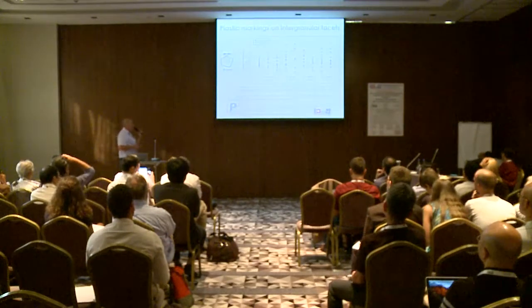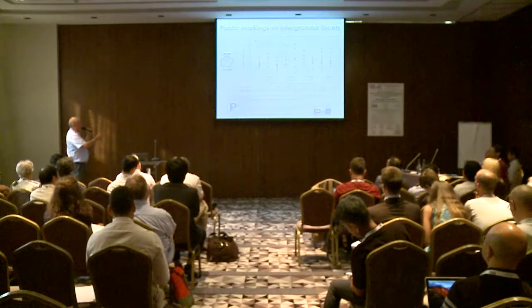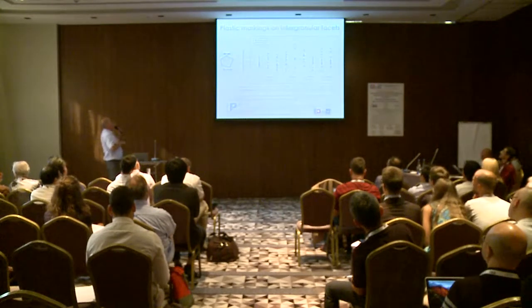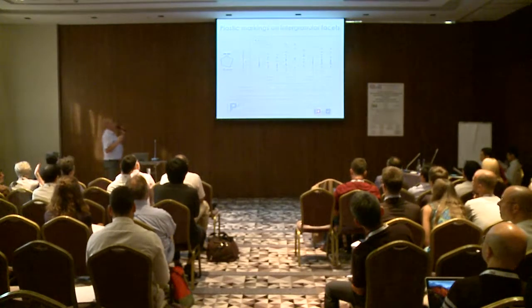So Tomoki performed a series of measurements of these spacings on fracture surfaces produced under different exposure conditions, different hydrogen pressure, different frequencies. Here you have the results. You can see that, of course, for certain exposure conditions, we have a scatter which is more or less pronounced, but the scale is not very large here. But if you consider the average value of these spacings, we can consider that they are more or less independent of the exposure condition.